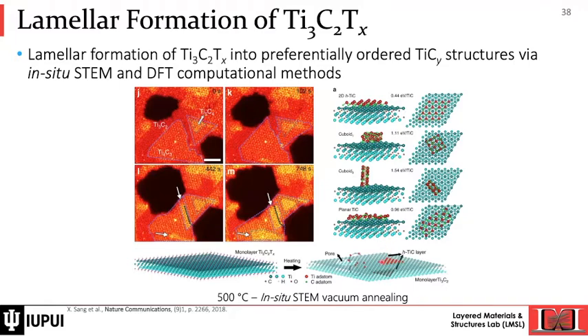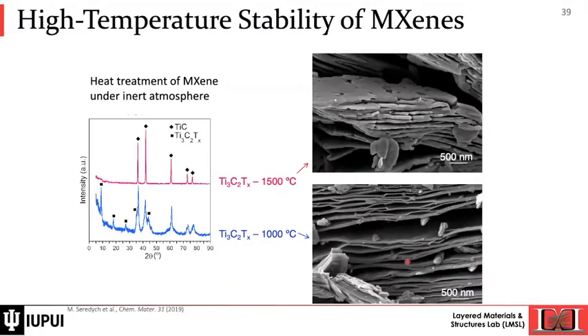So it is basically the 1-1-1 plane, but forming these thicker layers that we call hexagonal TiC, because they're off of the basal plane of MXene. So there is really no oxidation when we remove oxygen, obviously, and we can create carbides.